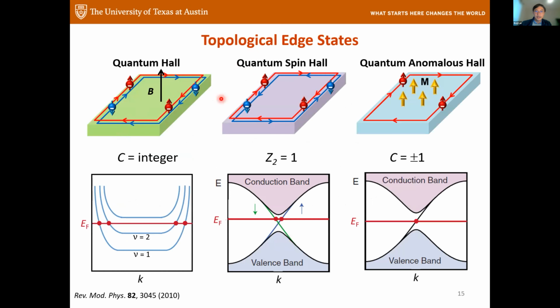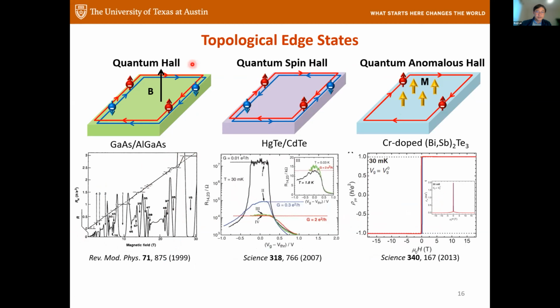There are a lot of quantum Hall related states with non-trivial Chern number or Z2 number. The bulk of these systems is either in a Landau gap or just a bulk gap, but the edges are conductive because of topology. There are either Landau states or edge states that cut through the Fermi level. Transport-wise, you see nice oscillations in quantum Hall effects, and you see the quantization of conductance or Hall resistance in quantum spin Hall and quantum anomalous Hall states. The theoretical picture is always topologically protected edge channels.